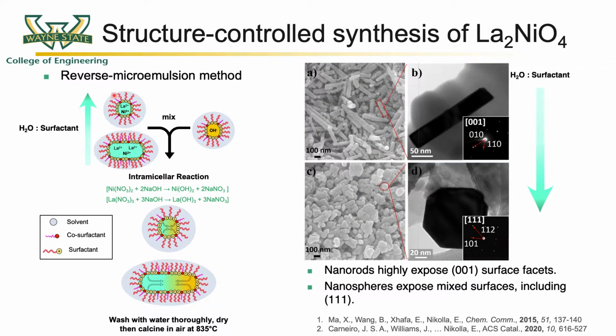We use a reverse microemulsion based technique to synthesize these rod-like nanostructures via varying the water to surfactant ratio during synthesis. As the water to surfactant ratio is increased, the synthesized oxide goes from a rod type structure to a spherical particle.